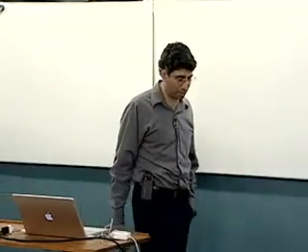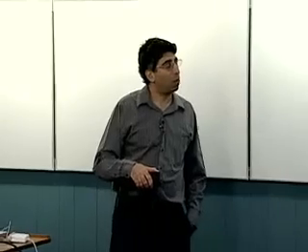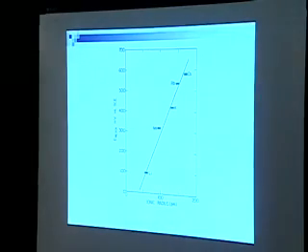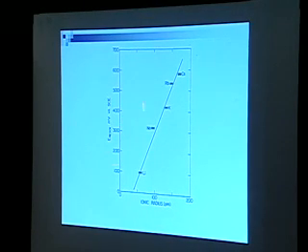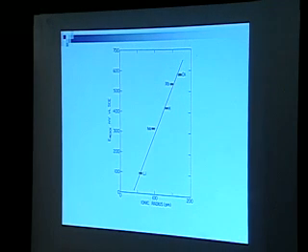And one thing I suggested is one interpretation of this data might be that, well, when the waters go into the lattice, they have to leave, and so there's a dehydration step, if you will, and there's a free energy associated with that, and that would get fed into this free energy, and so maybe this whole shift is just a hydration-dehydration energy term added on to the normal redox potential term that we're looking at.